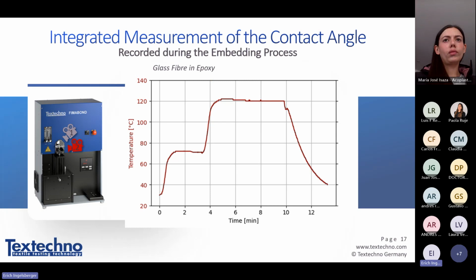Here we, for example, show a glass fiber insertion into epoxy. So this is thermoset, no more thermoplastics. You can see here the temperature profile of the heating system inside the Fimabond, which first prepares the matrix for embedding. In this period, we embedded the fiber. Then we bring this to curing temperature at a higher level. And then this is cooling down.